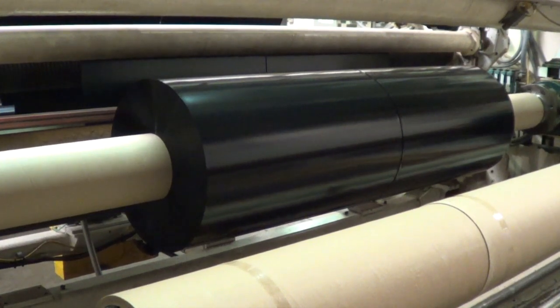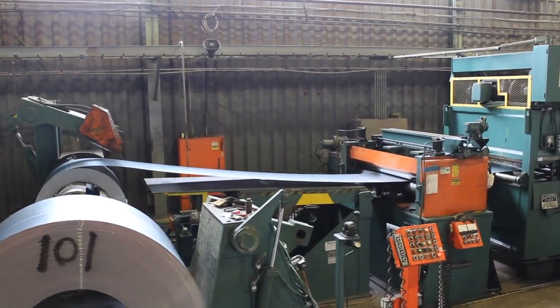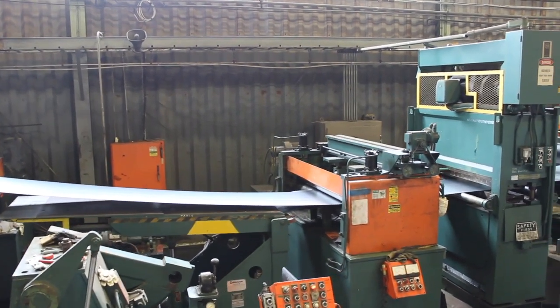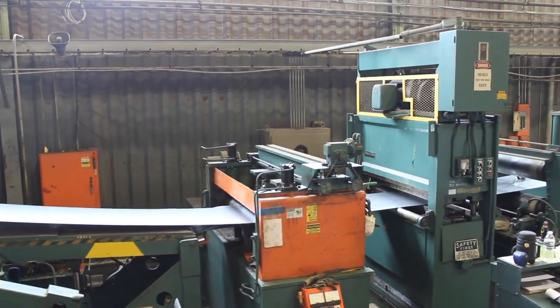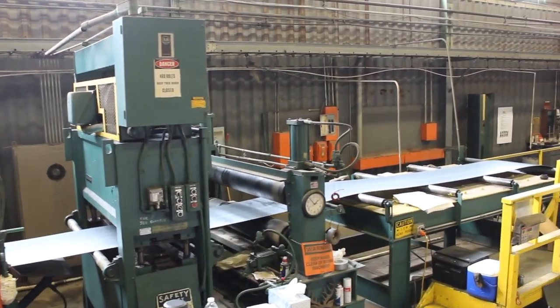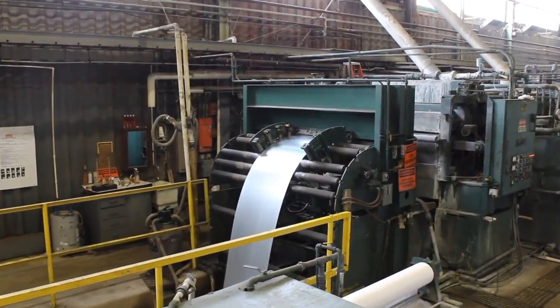The lamination process starts with a galvanized steel coil, which has been certified by the steel mill to meet all of the requirements for producing polymer-coated steel. The steel sheet goes through an alkaline cleaning tank to remove any surface contamination. It then proceeds through a four-brush Scotch-Brite machine to clean the coil of any contamination such as white rust or pre-treatment. Afterwards, the sheet moves through a double fresh water rinse tank that is continuously filtered, and then passes through squeegee rolls to ensure all excess water has been removed.